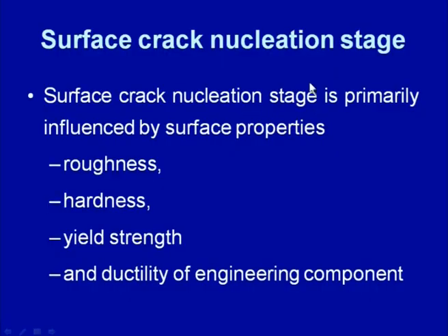But if we smoothen the surface, increase the hardness, increase the yield strength, and reduce the ductility of the material present at the surface layer, then these things will be discouraging the nucleation of the crack by the micro level deformation through the slip mechanisms. So if it is required to improve the fatigue life by delaying the crack nucleation stage, then the surface is finished, the hardness and yield strength are improved, and ductility is reduced.